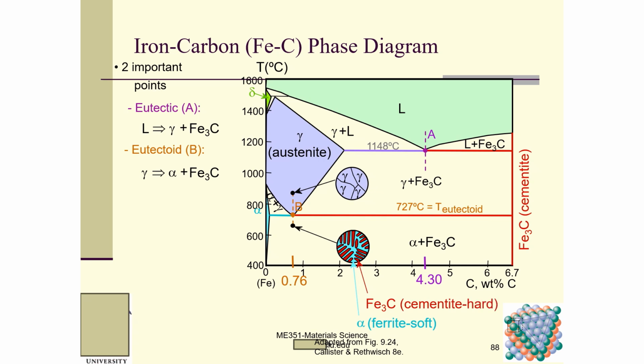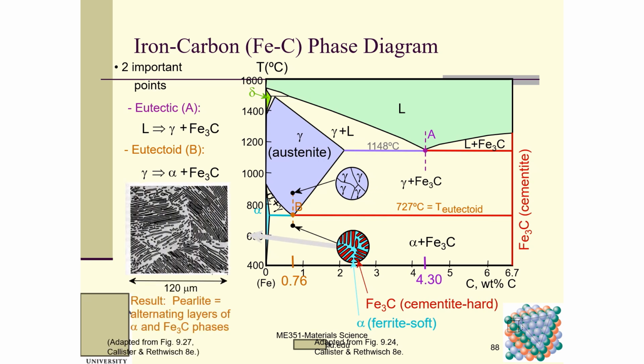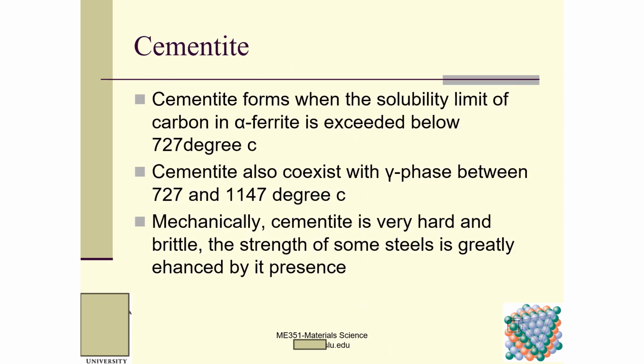This is a lamella, cementite, hard, cementite, Fe3C. So this is a micrograph. Cementite forms when the solubility limit of carbon in alpha ferrite is exceeded below 727 degrees C. So this is the 727 degrees C. The cementite also coexists with the gamma phase between 727 and 1147 degrees C. Mechanically, cementite is very hard and brittle. The strength of some steels is greatly enhanced by its presence.